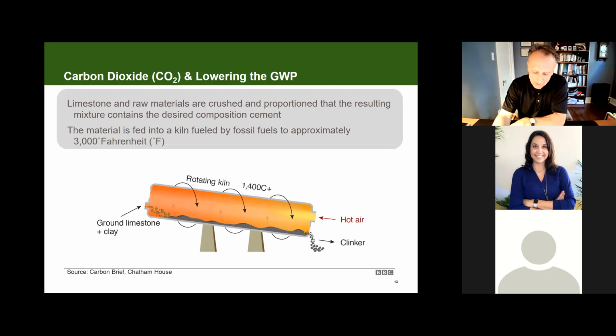Well, during the manufacture of cement, limestone and selected raw materials are crushed, milled, and proportioned in a manner that the resulting mixture contains the desired chemical composition that we're looking for in the finished cement. And all this material is then fed into a kiln, and the kiln is fueled by fossil fuels, heated to approximately 3,000 degrees Fahrenheit.